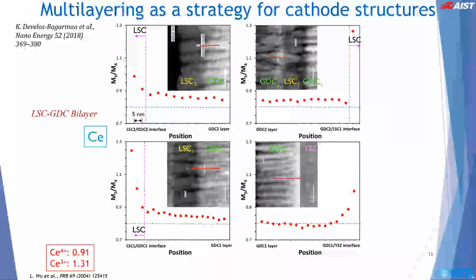We obtained the EELS spectra from various LSC-GDC interfaces and calculated the M5-M4 ratio as shown in this slide. Here, we can see that the M5-M4 ratio is well below 1 throughout the GDC region, implying that the cerium valence state within the GDC film is most likely cerium 4+. However, there appears to be an increasing trend at the GDC-LSC interface, where the M5-M4 ratio being higher than 1 indicates the presence of cerium 3+.